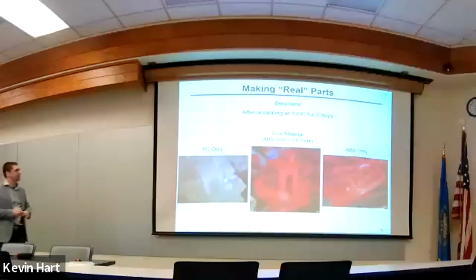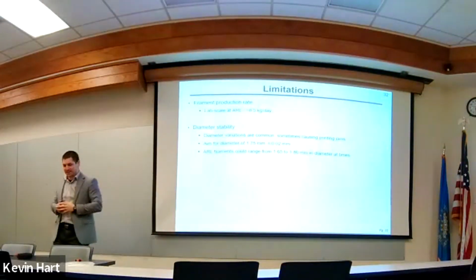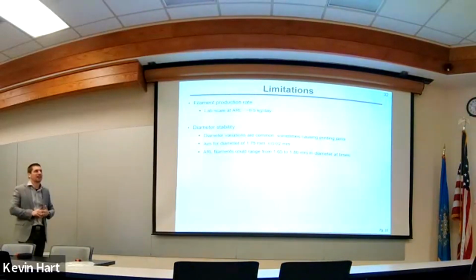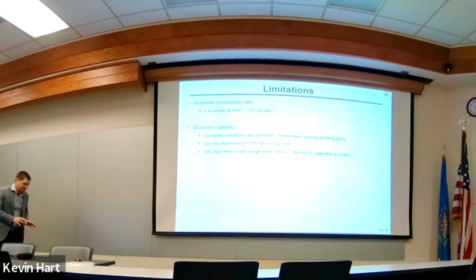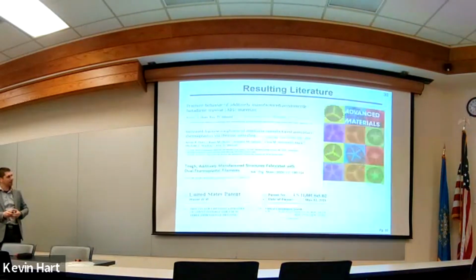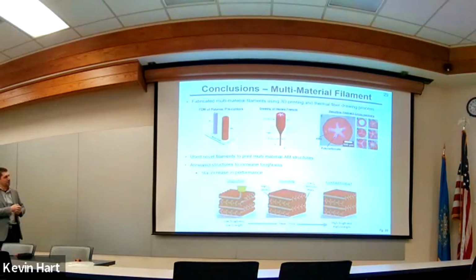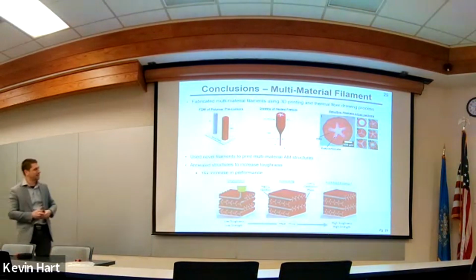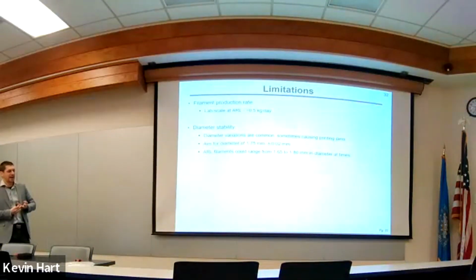All right, cool. So that's great, but there are limitations, of course. The biggest limitation of this is that you can't really make the filament that quickly. So this methodology that we used, where we print this guy, jam them together, put it in an oven, pull it down, and so on, you get maybe half a spool of filament out of that for a day's work, all right? Not ideal, okay? It takes a long time to make this filament. You don't get a lot of production out of it, okay? So it would be nice if you had a method to more quickly make this filament, all right?